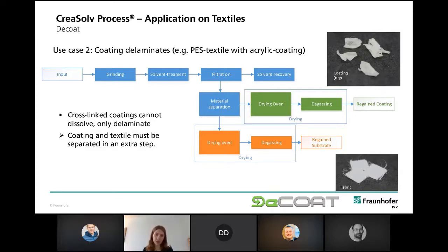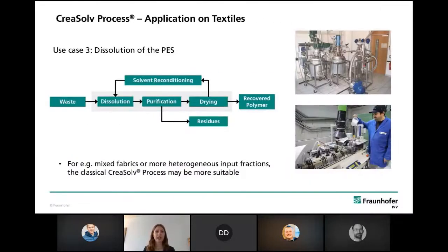And those two cases are worked on in the DECOAT project, but we also have one other option to treat textile waste with the CreaSolv process. And this would be the dissolution of the fabric itself. And this, for example, could make sense if we have more mixed waste streams again, or maybe also mixed fabrics, for example, a mixture of cotton and polyester. And in those cases, it would be possible to dissolve the polyester and then again, like I explained to you before, regain it from the solution. In our institute, we have a small technical plant where we can do this not only in the lab, but also in a bigger scale, as you can see it on the picture already.